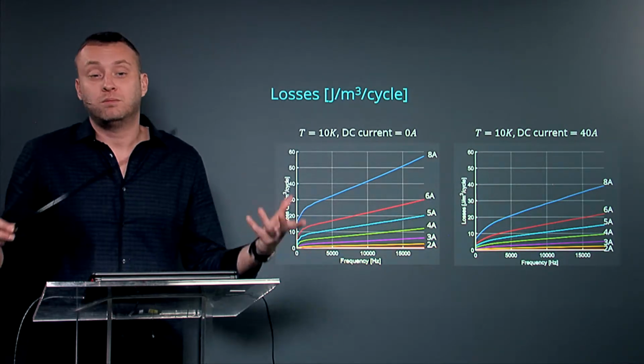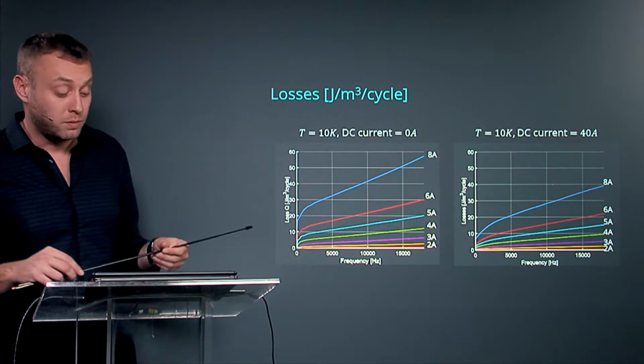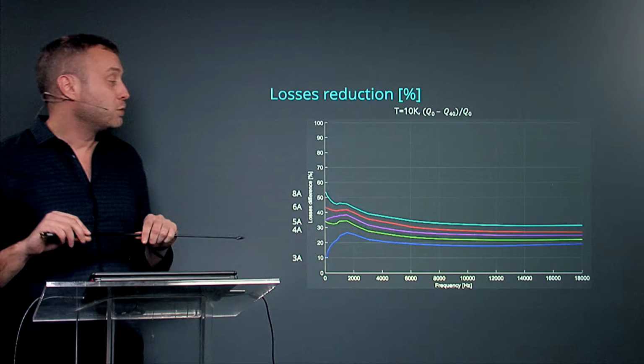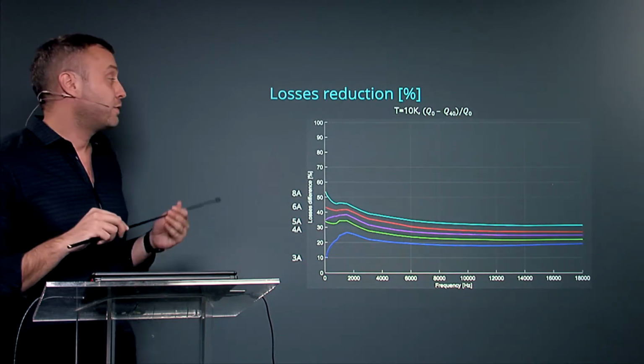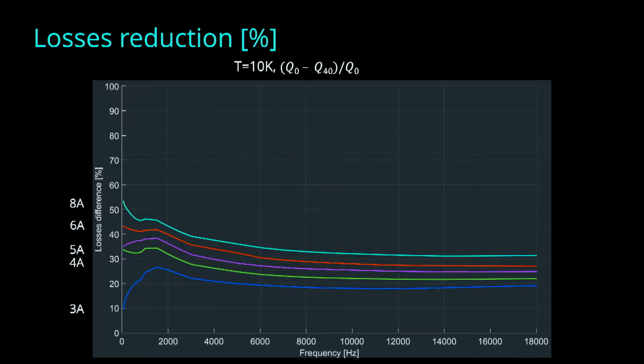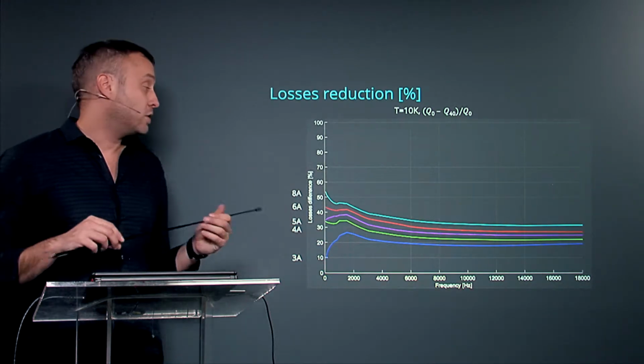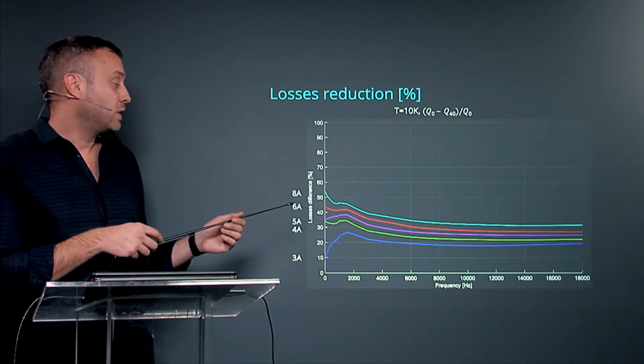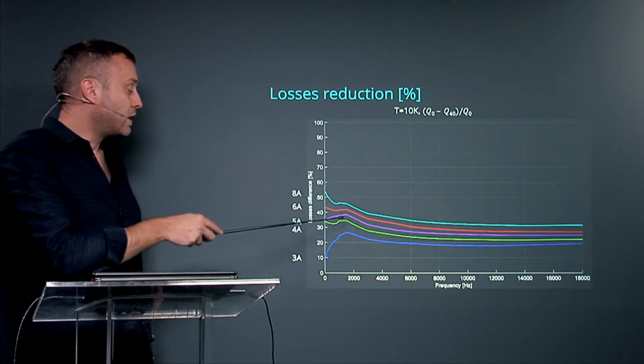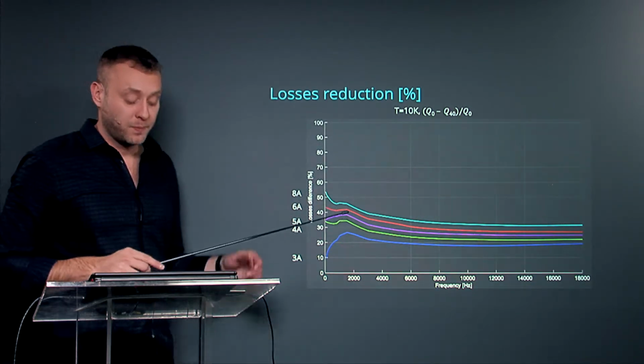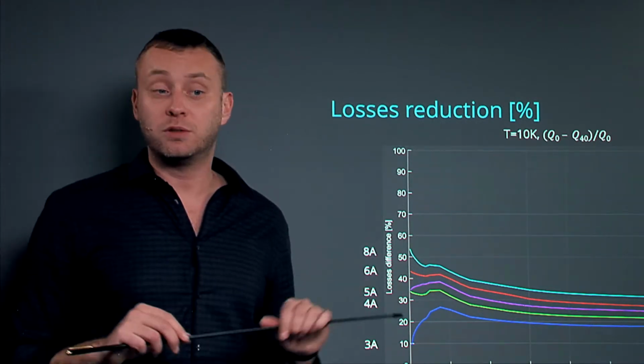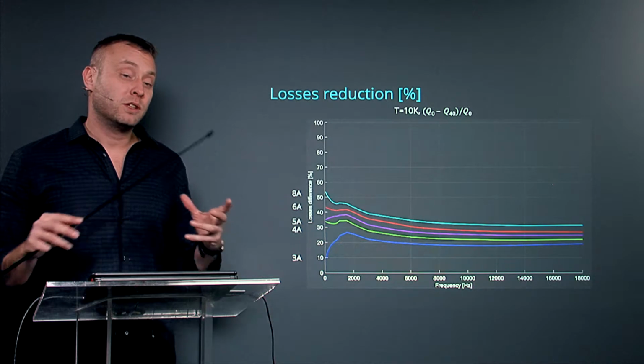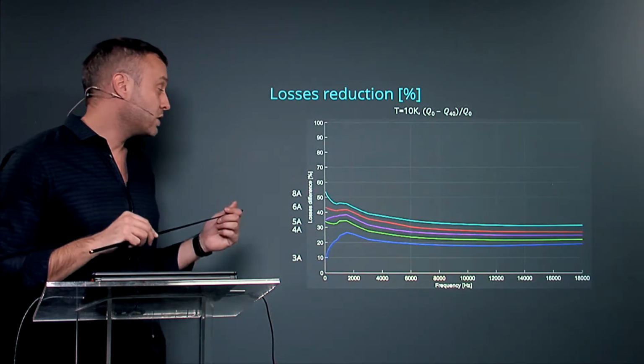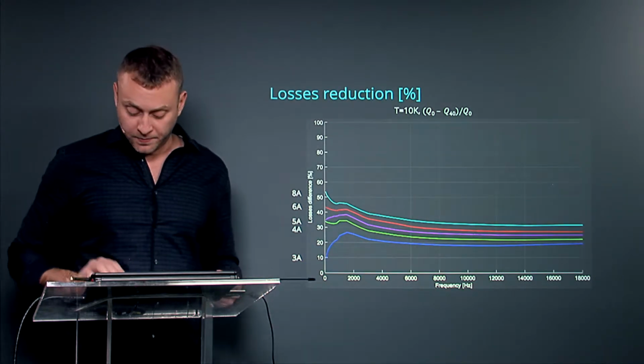That's a quite surprising result, because usually when we add more current, the energy loss should be higher. To compare those two cases, I want to show you the loss reduction between the case with the DC current and without. So we can see the reduction is about 50%, which is a huge number, but it's not constant. It depends on frequency from one point, and it depends on current amplitude from another. These results are quite counterintuitive, because there is some interrelationship between the DC current and the frequency, and they affect each other in this case.